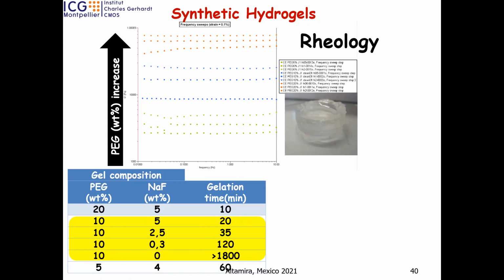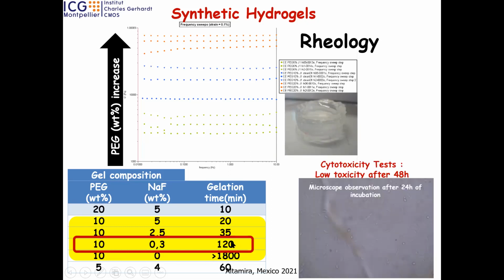3D printing. So the idea is we focus on this condition, because we don't need a very fast gelation time, and not a very slow gelation time either. The idea is 1 hour, 2 hours, 3 hours, that's okay. So we selected 10% of biopolymers and 0.3% of sodium fluoride, and you can get your hydrogel like this one after 2 hours.